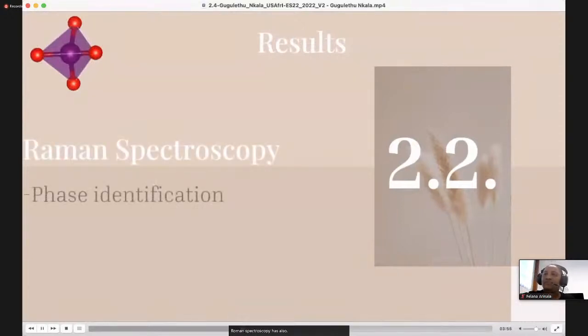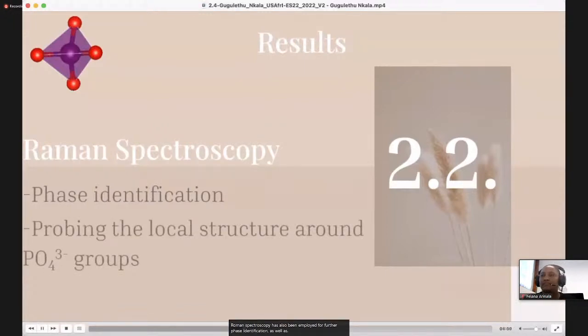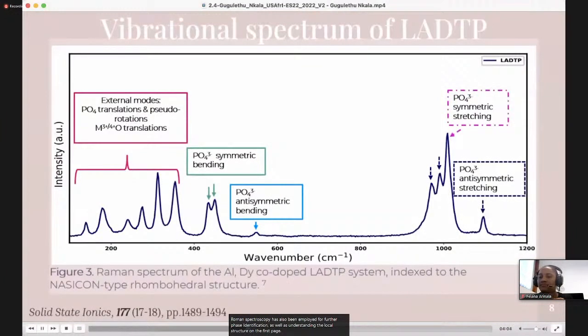Raman spectroscopy has also been employed for further phase identification as well as understanding the local structure around the phosphate and titanium groups. The vibrational spectrum of LADTP has been indexed to the NASICON-type rhombohedral structure, which is what has been reported from XRD, as well as no detected phases of dysprosium and aluminium phosphate. The spectrum consists of external modes that are due to phosphate group translations and pseudo-rotations, as well as the metal-oxygen translations. Above 380 wave number, we have the symmetric and antisymmetric bending and stretching modes of the phosphate and titanium groups. This technique is insightful in terms of understanding these phosphate and titanium group changes, but it has not provided significant information on what happens to the metal-oxygen regions.